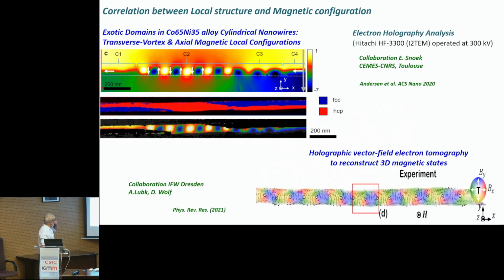Also in collaboration with Etienne Snoek in Toulouse, it was possible to correlate this local magnetic structure with these vortices with the local hexagonal crystalline structure of the nanowires. So the red part is the hexagonal, and the blue is FCC. So we have this exotic vortex domain structure just in the region where we have hexagonal symmetry. Also, we were able, in collaboration with people in Dresden, to obtain the same information as we got there.